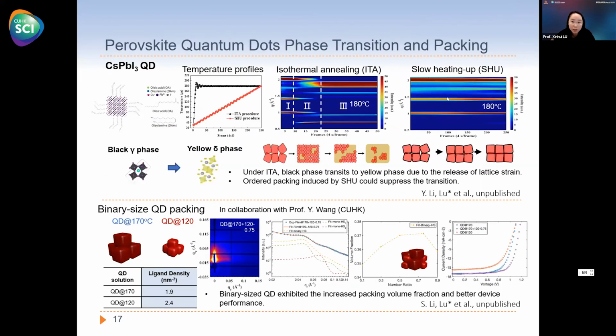So recently, we are trying to understand the phase transition of perovskite quantum dots and how the packing affects the phase transition. The behavior is quite different from the bulk film, because the surface ligand on the quantum dot will stabilize the black phase, which is not possible in the bulk film. However, when we heat the sample, it will still transfer from black phase to yellow phase. But if we slowly heat the sample, it can stabilize in the black phase.